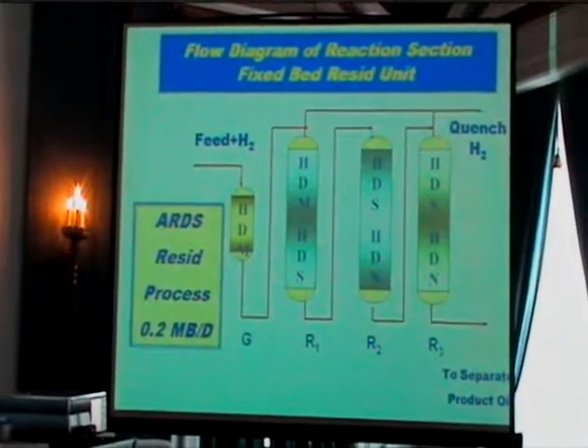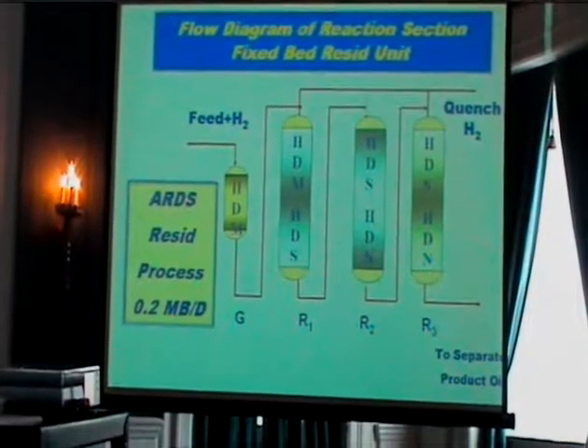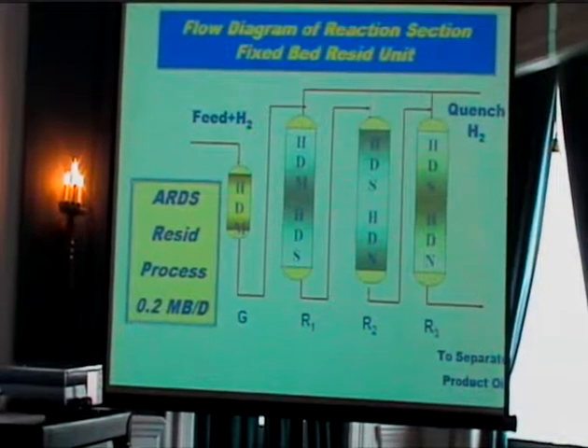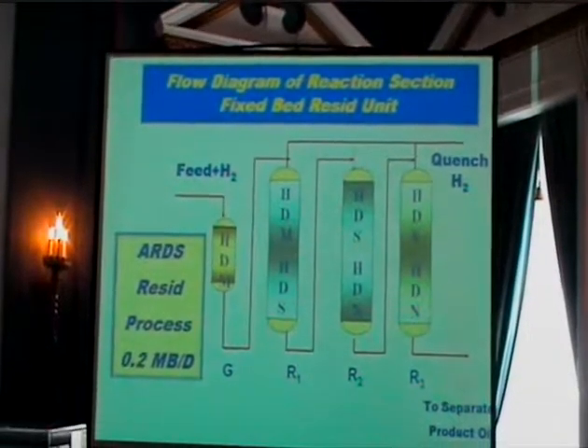We might end up with five to six catalysts in a catalyst system, and this comes from the complexity of the feedstock. The feedstock is normally an atmospheric residue with a high amount of metal, carbon, sulfur, and asphaltene. Each catalyst will be dedicated to removing certain heteroatoms. The main objectives of the ARDS process, in Kuwait in particular, is to produce low-sulfur fuel oil and feedstock for downstream processes like FCC and also for hydrocracking.